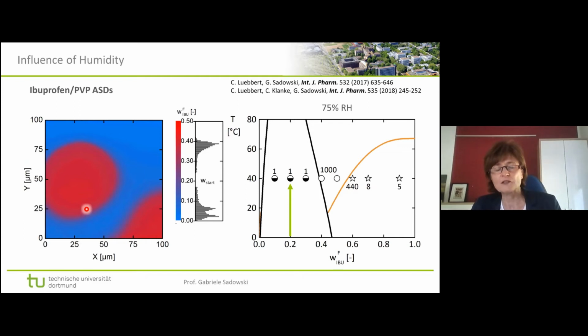And the very scary thing for the pharmacist was that the target concentration indeed was 0.2. So this is the green arrow here. This is the concentration they wanted to have in their tablet. And if you look at this diagram, then you see there is indeed not a single point in the formulation where you have this target concentration, but instead you have two peaks here, one at about 0.4 and one at about 0.05. This is really a huge difference in API concentration in the two phases, and it very nicely also fits with our prediction. So this is 0.4 and this is 0.04. So this is really, again, a very nice proof that the phase diagram is probably very reasonable.